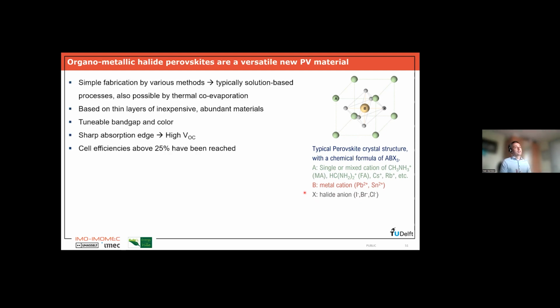Now, what are some of the features that make this material very successful? First of all, you can fabricate it very simply. Typically, solution-based processes are possible, and you can also grow it by thermal co-evaporation. That means you have inexpensive ways of growing the material. Moreover, you don't need a lot of the material. You need only 100 nanometers to make a good device. And it's an inexpensive material consisting of abundant elements. So this makes it very interesting from a cost perspective.